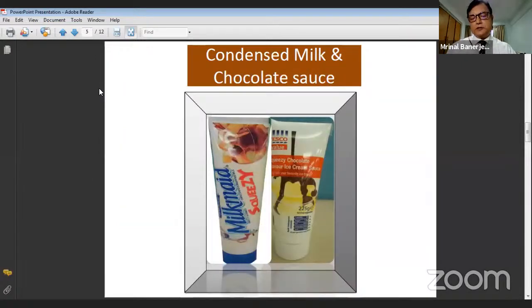Yeah, this condensed milk, as you know, is from Nestle only. We did it many years ago, almost 15 or 18 years back, in India itself. However, going forward, I think Nestle had an issue with ITX, which came from the printing inks, because all tubes are generally printed on the surface with UV curing ink. And ITX all came from the photopolymer. Now we are getting ITX-free and nonylphenol-free UV inks, but at that time it was not available. It was not our tube, but Nestle had one consumer complaint and there was a case, so they stopped making Milkmaid tube here in India.